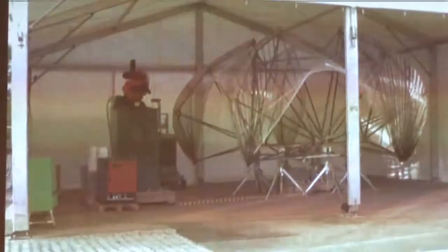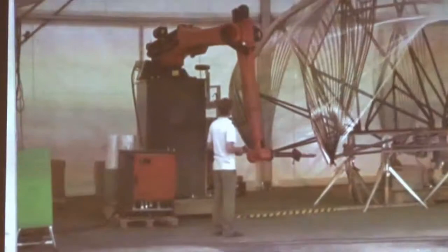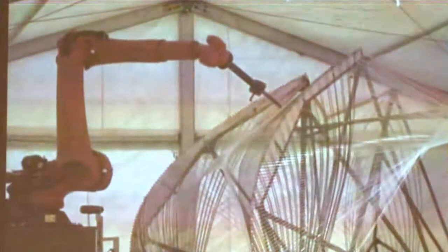A couple of days later, it looks like this. The first layer of glass fiber is laid, and this layer of glass fiber, this white glossy material that you can see, becomes the actual formwork onto which the structural carbon fiber is subsequently laid. You can also see that the curvature the carbon fiber takes on is quite a complex shape, and this all needs to be pre-computed in its interaction with the previously made material layers.